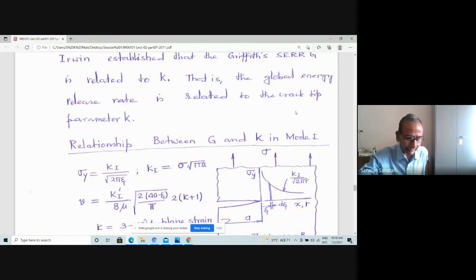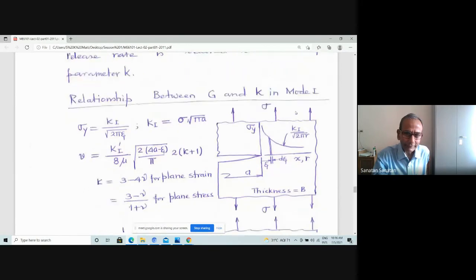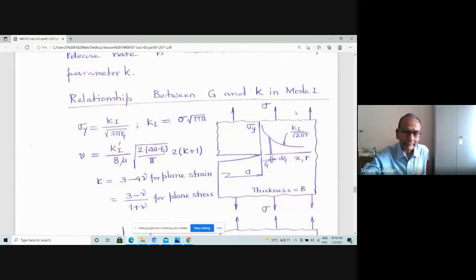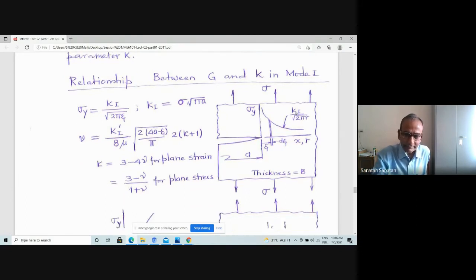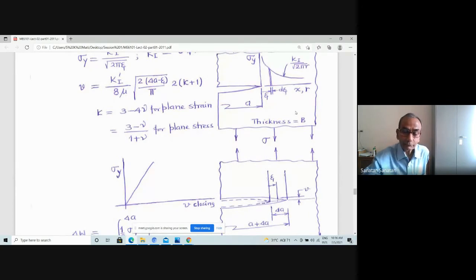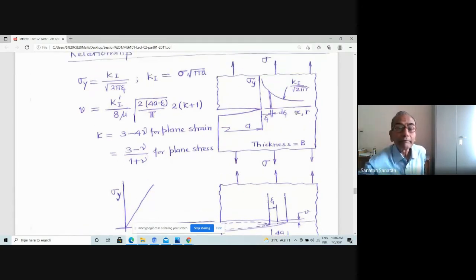So that is something which we would like to see, and it is all mathematically established. We would like to consider how we get the relationship between the strain energy release rate G of Griffith and the stress intensity factor at the point of onset of crack extension. So he took up the case of mode 1, and what he considered is a picture in which we have a crack of size A in a uniformly thick plate, subjected to remote loading sigma.